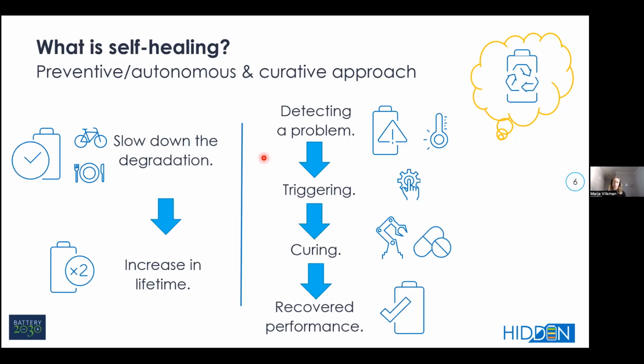So sometimes there is a problem which we were not able to prevent. So then we will need some curative ways to heal the battery. And that requires triggering. So we need to, first of all, know that something is going wrong. We will detect a problem. Then we will trigger the self-healing method with either some mechanical improvement of the cracks in the battery, or some chemical treatment like pills here. And then we will achieve the recovered performance for the cell.